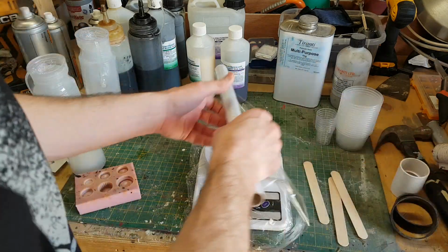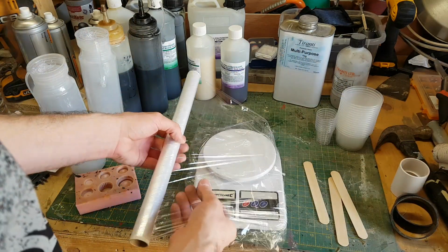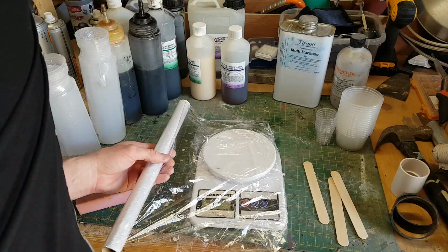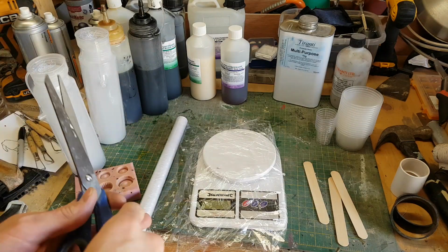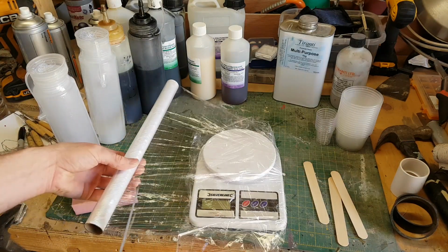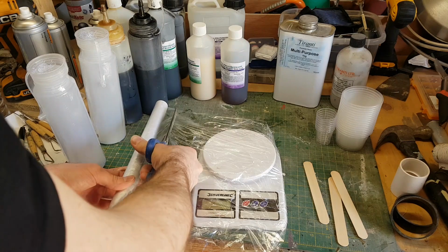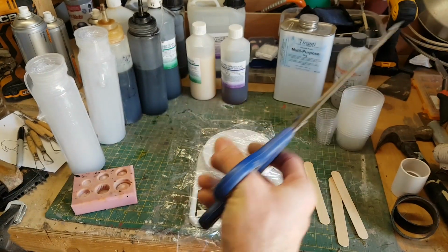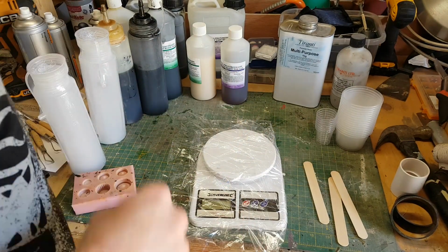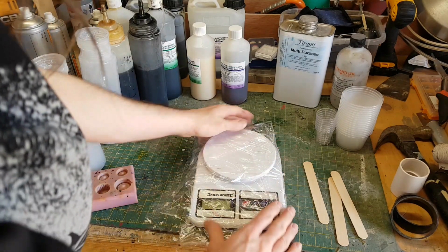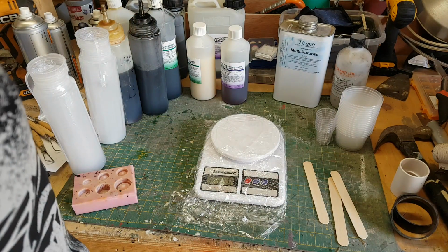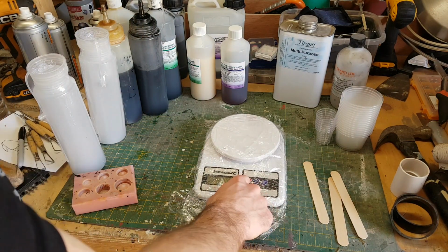One thing I will say is, because of the type of casting that I do, generally casting quite small parts, I do sometimes find that I'm mixing up very small amounts of resin. And these scales work well enough, but if it's only like 4 or 5 grams, I'm not entirely confident that it's accurate. So what I have been thinking of doing is getting some jeweler's scales, which are much, much more accurate. If you're doing this type of casting as well, you may well find that they're useful. I haven't tried it yet, but it's something I do intend to do.